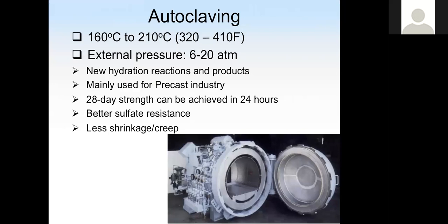For autoclaving, the curing temperature is very high, above the boiling temperature of water. But because the pressure is also very high, the water in concrete will not actually boil. So high temperature and high pressure. Then we have new hydration reactions and new hydration products. It is only used for the precast industry, because the autoclaving chamber is very big. We cannot bring that to the field. So 28-day strength of concrete can be achieved within the first 24 hours, a very fast turnaround time. And also because we have totally new hydration products, the concrete will have better sulfate resistance and also less shrinkage and creep.